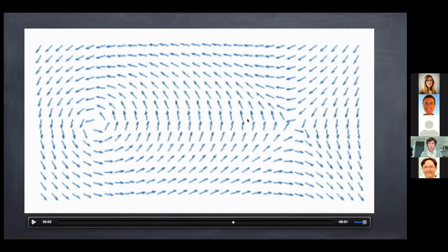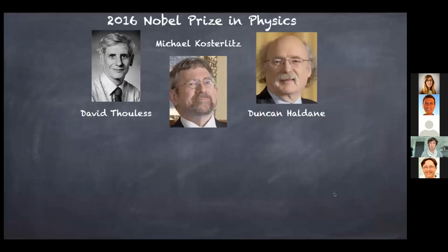So when they're some finite distance apart from each other, it turns out that even as the lattice size goes to infinity, the total energy contribution now converges. So the divergence from the vortex and the divergence from the anti-vortex just perfectly cancel each other out enough so that the total energy on an infinite lattice is now finite, which I think is an interesting thing.